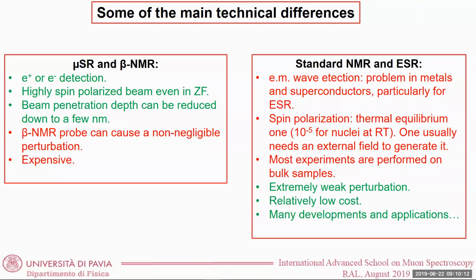However, there are some drawbacks. So let's say for beta NMR, the problem is that you are putting inside your sample a big nucleus. Usually it's a low atomic number nucleus, like, for example, lithium, but still it is a big perturbation to your system. And so, in the case of beta NMR, what you are introducing with your beam is a non-negligible perturbation. It can cause defects, and so that's a drawback.